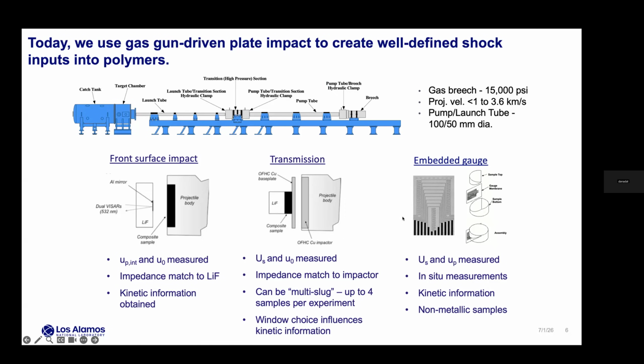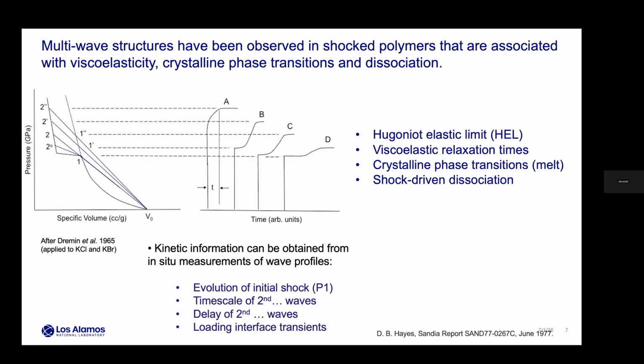And then lastly, one of the unique diagnostics we have here at LANL is embedded gauge techniques, which we apply to polymers because they're non-magnetic. And so this is based on electromagnetic gauging. And so we can then observe the evolution of the shock wave as it travels into the materials. So I'll be showing some examples of data from these types of experimental techniques. And of course, obviously, there are laser drive techniques, which we also employ. We haven't done as much in the polymer area using laser drive techniques, but certainly other groups have.